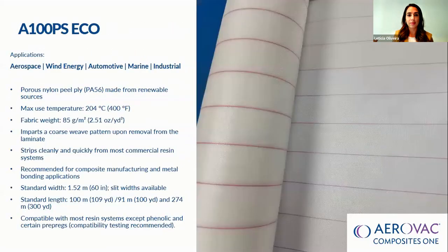This is A100PS ECO. We can use it for different applications like aerospace, wind energy, automotive, marine, and industrial as well. It is a porous nylon 5/6 peel ply, maximum temperature 400 F. It also has a standard size, but you can split it. It's easy to see in the process because it has a print stripe. And after we remove it from the part, it's good for second operations like painting or bonding. It's recommended for most resin systems except phenolics. So sometimes with phenolics it's good to do some tests to make sure that it's compatible.